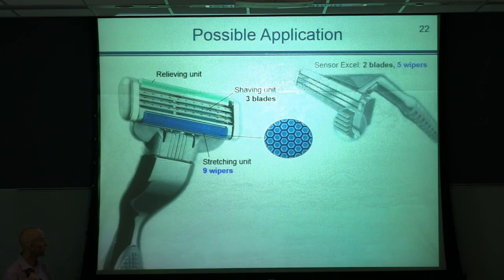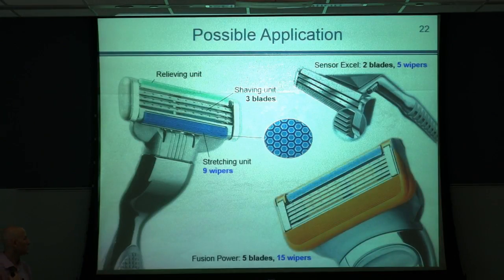Now, how were we sure that friction is important here? If you look at the evolution of safety razors, you can clearly see that the number of wipers found in this stretching unit is proportional to the number of blades. When Gillette just came to the market with their Sensor Excel, they had only 2 blades and 5 wipers. The next one had 3 blades and 9 wipers, and what we have now operates based on 5 blades and 15 wipers, meaning that roughly speaking each blade requires 3 wipers to have the skin sufficiently stretched. So we wanted to test how our hexagons operate in this unit.